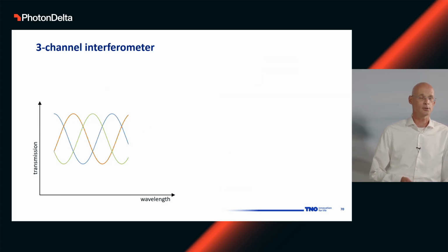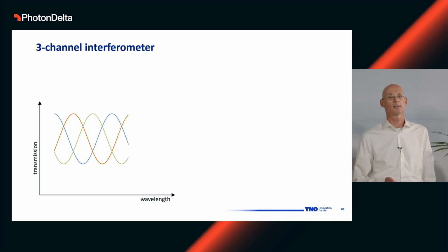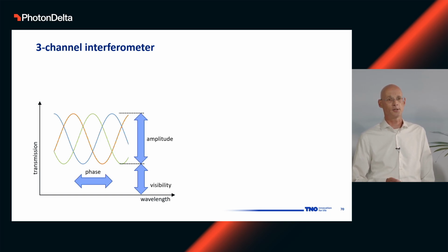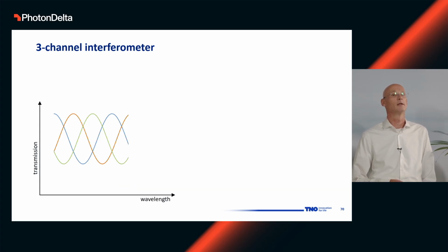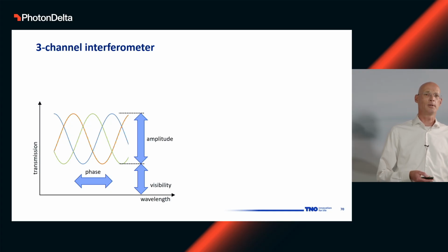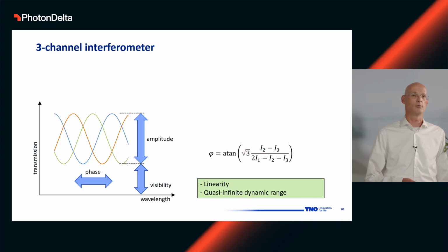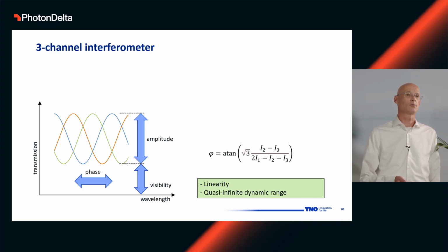Now we like 3-port interferometers because the interferometer response actually has 3 unknowns, which are the amplitude, the phase, and the visibility. The visibility is essentially the modulation depth. And in order to know 3 parameters, you also need to measure 3 things. So you can solve an equation with as many unknowns as parameters. And what you can do is calculate the phase, which is proportional to pressure, by a simple equation, provided that you have 3 outputs of your interferometer. The key thing here is that now the phase is linear with pressure, and the dynamic range is quasi-infinite because you can just keep on counting those fringes. And linearity and dynamic range is something we really like.